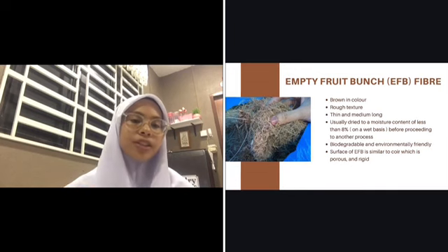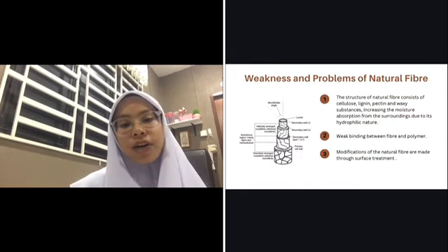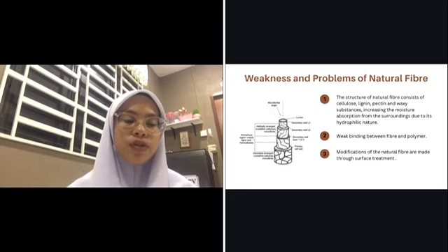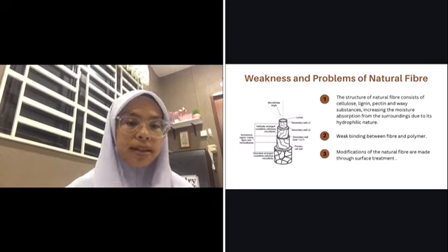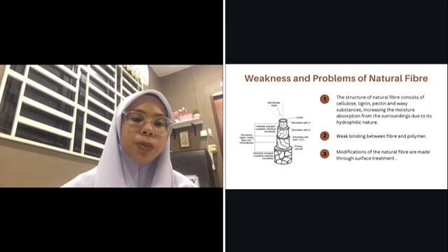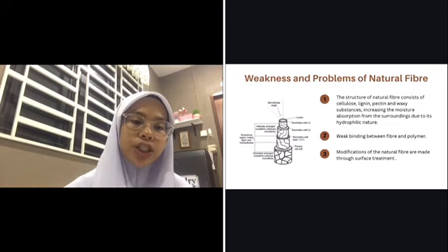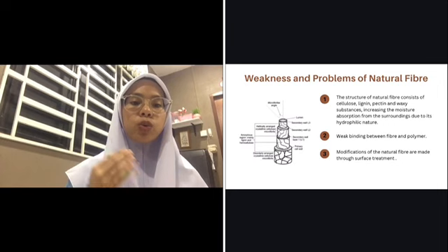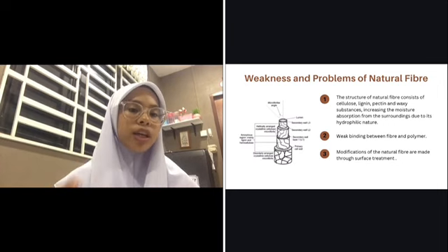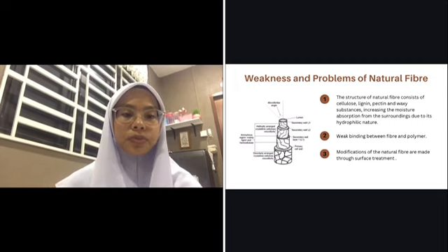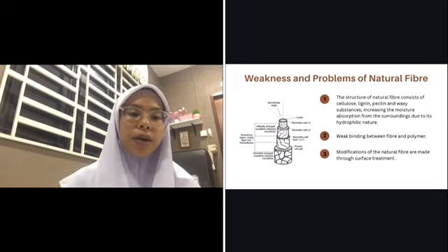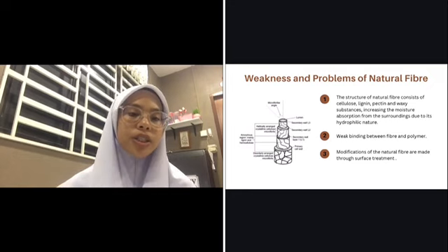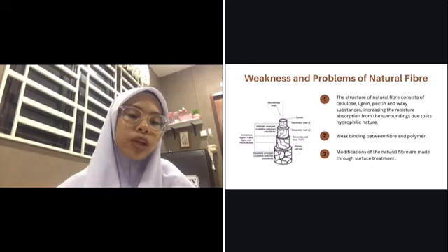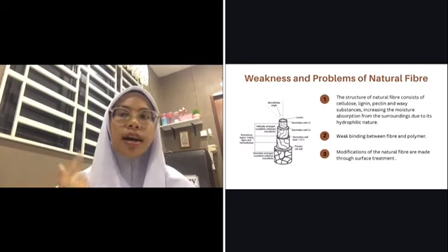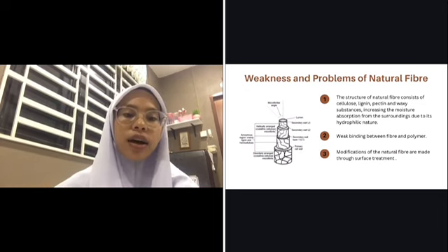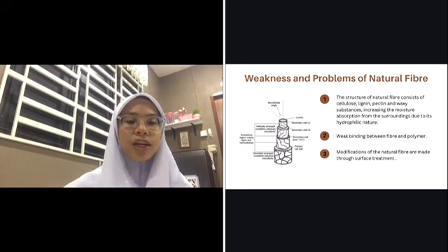Unfortunately, natural fibers also have their weaknesses and problems. For instance, the structure of natural fiber consists of cellulose, lignin, pectin, and waxy substances, increasing the moisture absorption from the surroundings due to its hydrophilic nature. This consequently causes a weak binding between fiber and polymer. Due to this, modifications of the natural fiber are made through surface treatment to increase the roughness of the fiber surface, besides reducing the moisture absorption of the fiber. Fortunately, the weakness of the empty fruit bunch fiber, which is its high water absorption rate, can be partially overcome by applying the alkaline treatment to the fiber.